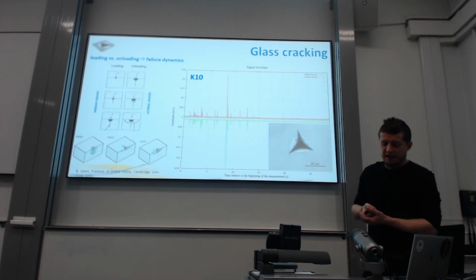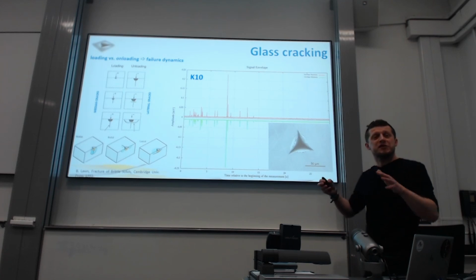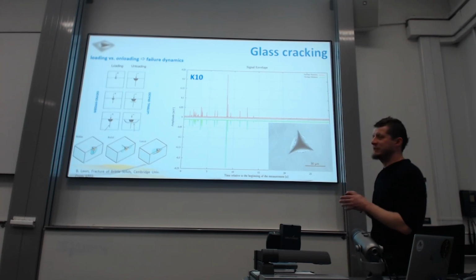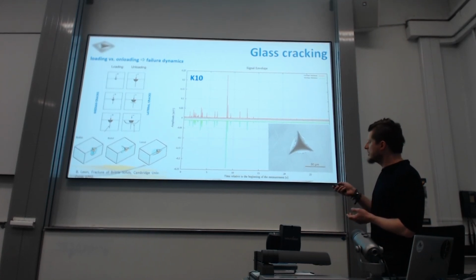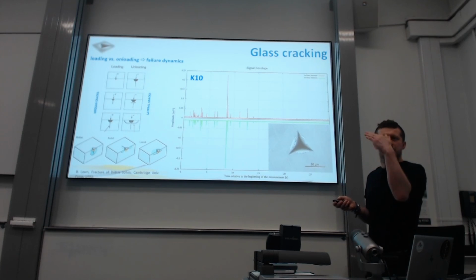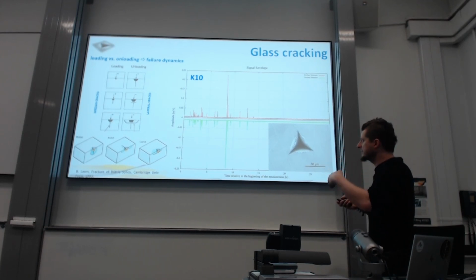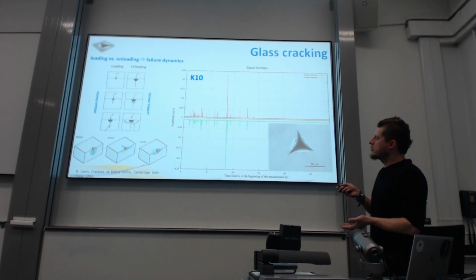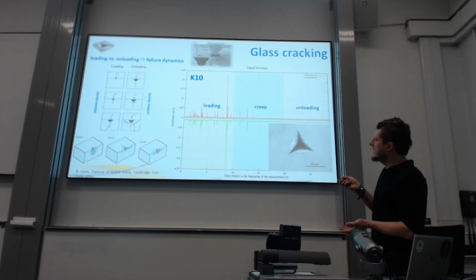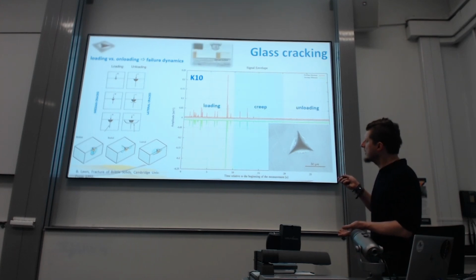Okay, I promised even some non-scratch tests. So here are some indentations. In indentation, you have a loading phase, a dwell phase, and an unloading phase. And what you would expect is that most cracking happens in the loading phase. But there are even some cases in the creep or dwell phase.